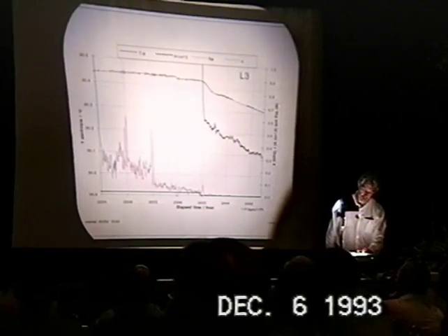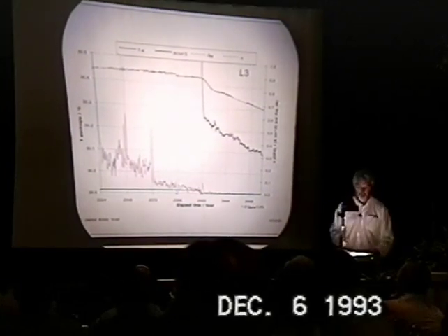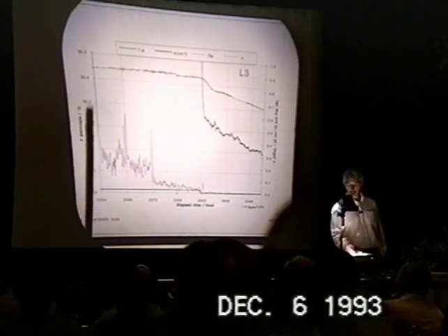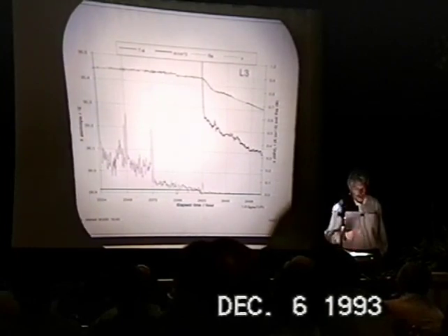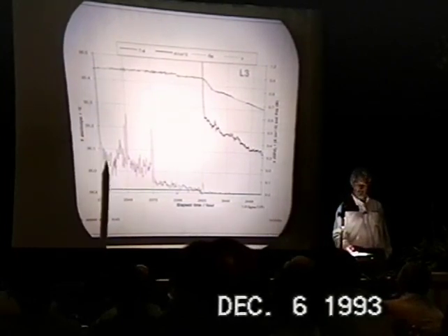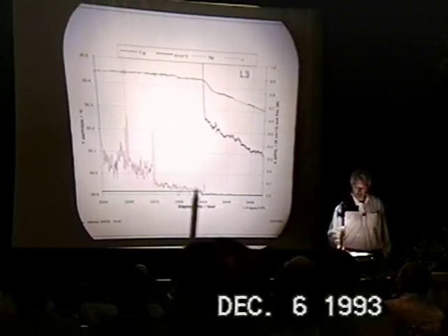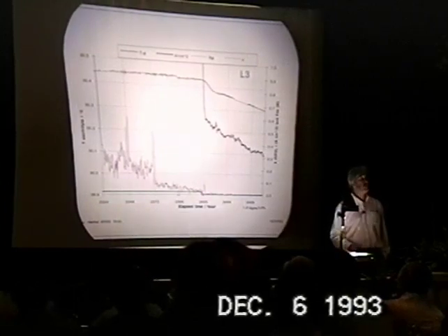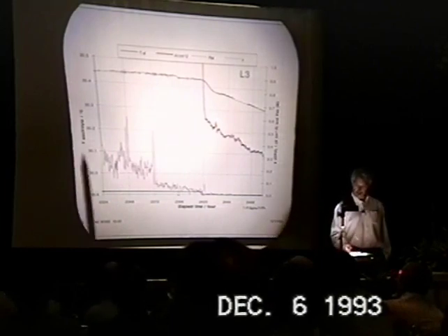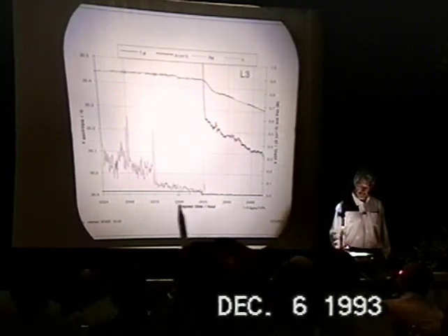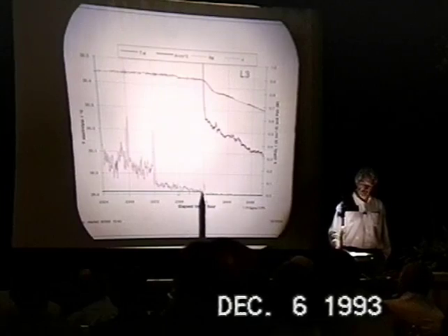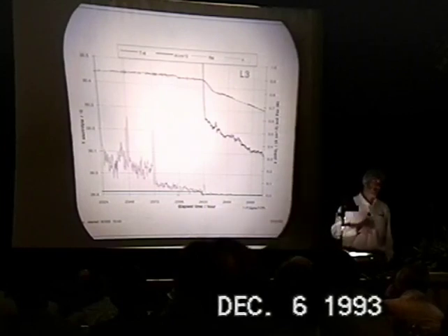That is a very, very small amount of electrochemical input current. Nevertheless, the excess power, which is represented in pink by this jagged curve here, comes down, yes, it doesn't come down to zero, it comes down to about 200 milliwatts. And then as these days march by, in 4 or 5 days, this excess power drifts down towards zero. At this point, we reverse the polarity, or at least we turn the current down from 23 milliamps per square centimeter cathodic to 1 milliamp per square centimeter anodic.